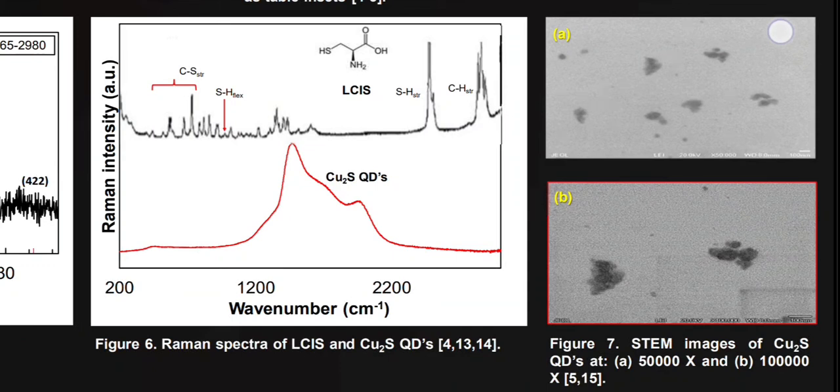The obtained crystalline phase and crystalline diameter were confirmed with X-ray diffraction observations, supporting the advantage of using LCIS to mediate copper sulfide nanocrystal growing. Also, stoichiometry is demonstrated with the absence of localized surface plasmon resonances.